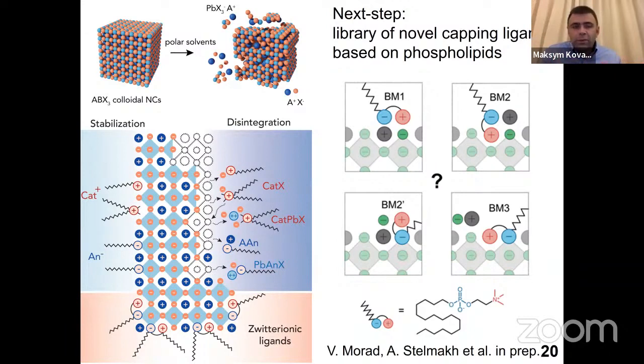Now, as you've seen, when we use alkyl ammonium ligands, they do bind non-covalently. They replace cesium, as we discussed before. Such alkyl ammonium displaces a surface cesium ion and inserts the head group into this pocket. A similar approach you can do with anionic ligands. They will displace surface halide and insert themselves. But an even bigger problem is that it's easy to overdo this, because as you add more of these ionic ligands, they start carving into your material, they etch it. And it's always tricky to find a balance.